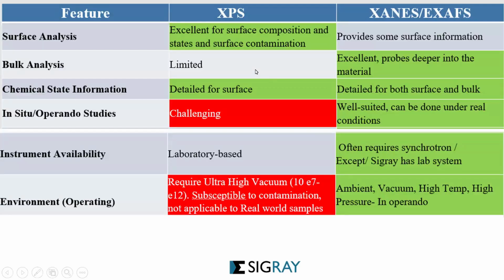And you will look at XPS, because they require ultra high vacuum, 10^-7 to 10^-12. So it is extremely susceptible to contaminations that are introduced, and therefore they are generally not used for real world samples. Whereas with XANES or EXAFS, you can run it in ambient, in vacuum, in high temperature, and high pressure, and in operando to mimic the real operating conditions.